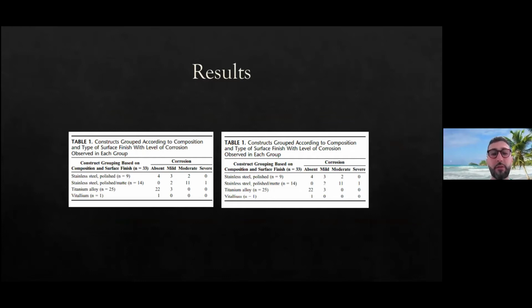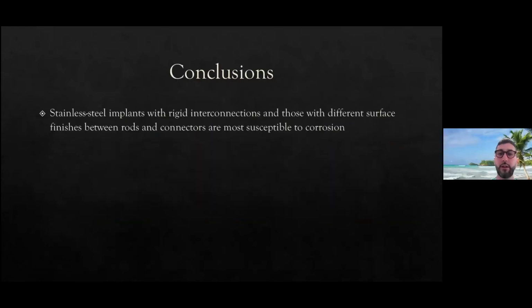Titanium had a small amount of corrosion, and Vitallium, which we're not going to talk a whole lot about, it's not used a ton in our field. It's used more in dentistry and sometimes in pediatric cases. It's something similar to Cobalt Chrome, really had no corrosion. And the more interesting finding about this, because it's kind of well known that stainless steel has more corrosion than titanium, was that the finish of the stainless steel seemed to contribute to that. And the reason that they hypothesized is that those different surfaces, so the screw being polished and the rod being matte, created more friction, and that led to more corrosion.